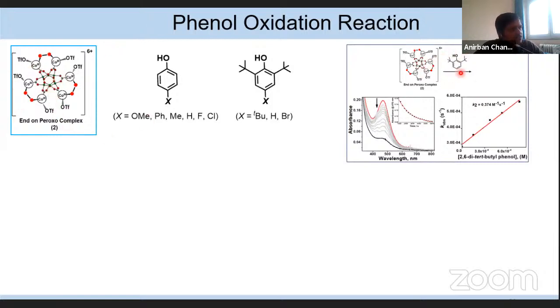Here I show the reaction of this end-on peroxo species 2 with 2,6-di-tert-butylphenol, and you can see the addition of an excess amount of phenol decreases the characteristic absorption band, which follows first order kinetics, and from there I can determine the second order rate constant value K2.